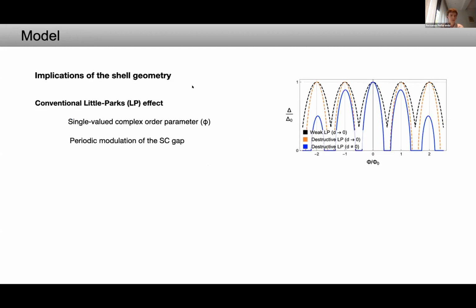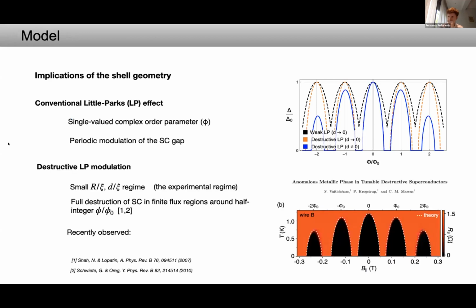So as we already see, when we have superconducting cylinders threaded by a magnetic field, the order parameter has a periodic modulation as a function of the applied flux. This is due to the single-valued character of the complex order parameter phi. However, deviations from this behavior, depicted in this graph as a black dashed line, were predicted to exist for cylinders with radius and thickness much lower than the coherence length, as is the experimental regime.